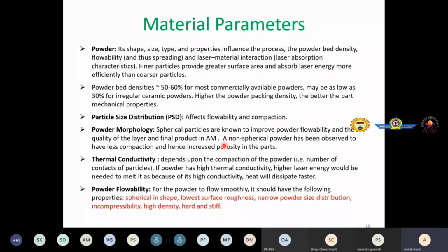The thermal conductivity of the powder material is important, right? If the powder has very high thermal conductivity, heat will not remain focused, but will diffuse, and in that sense you would need higher laser energy to create the melt pool. For example, aluminum powder faces this problem. Copper powder faces this problem. Then powder flowability: for powder to flow smoothly during powder layer generation, it should have the following properties: spherical in shape, lowest surface roughness, narrow powder size distribution, incompressible, high density, hard and stiff, so that the recoater can easily handle them. So if we are talking about metal powder particles, a metal recoater should be okay. But if we are talking about polymer powder particles, a metal recoater may not work. We may need some plastic recoater.